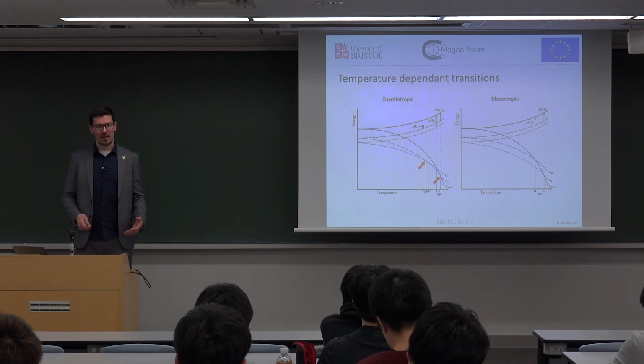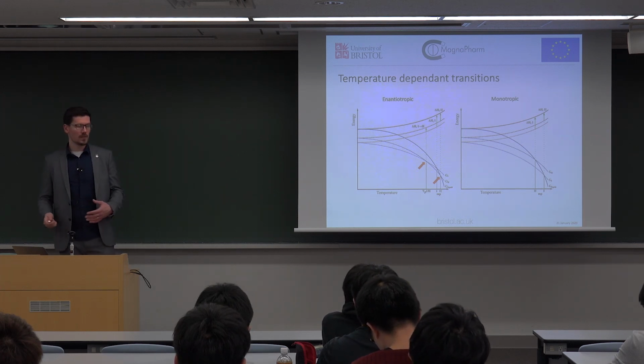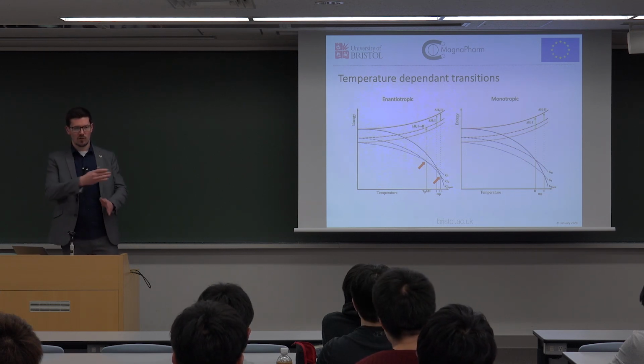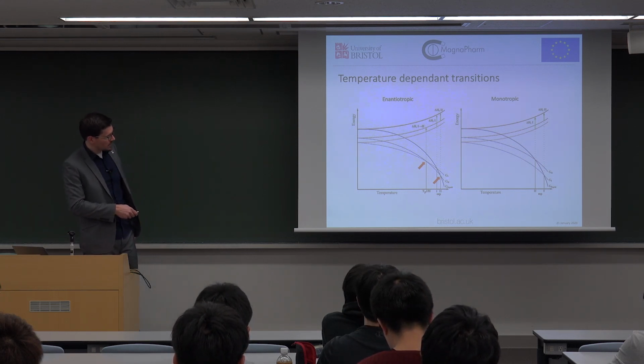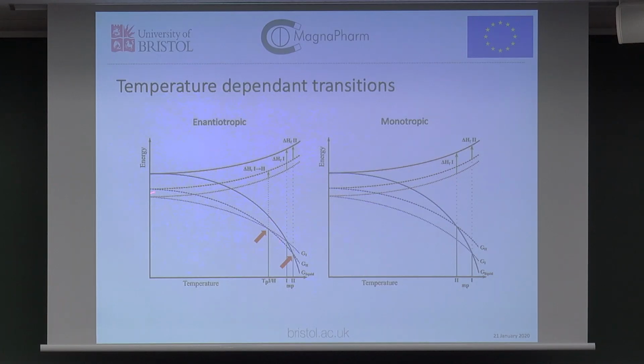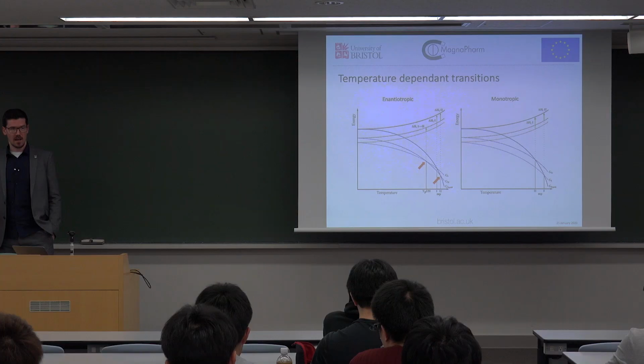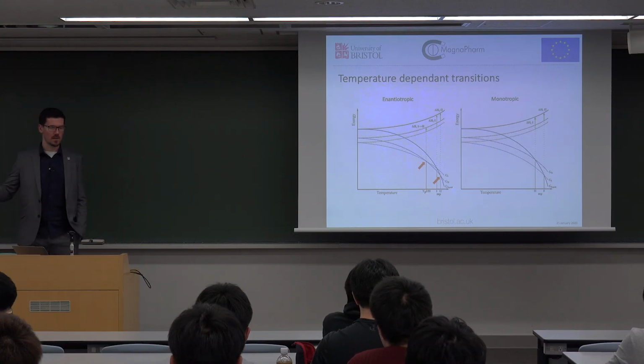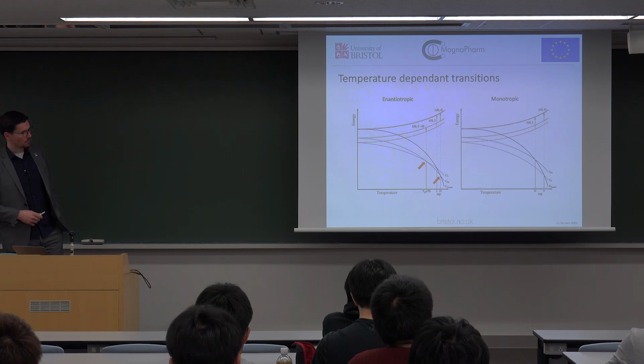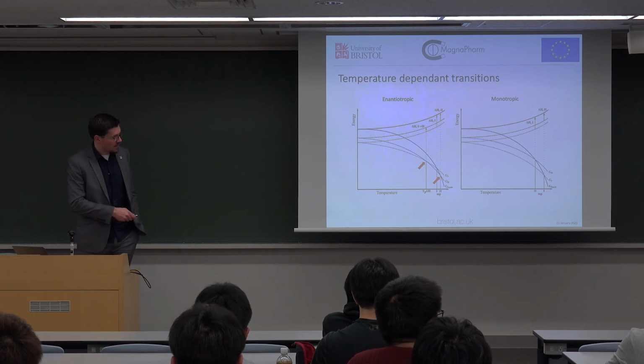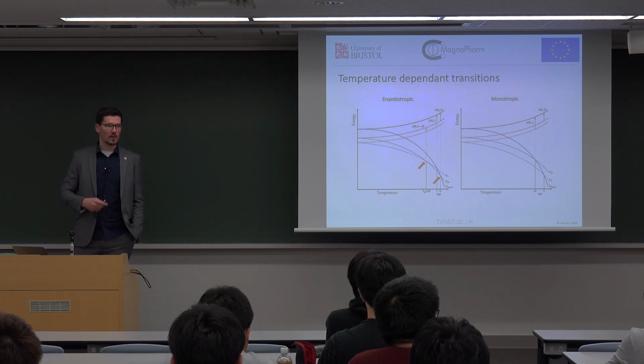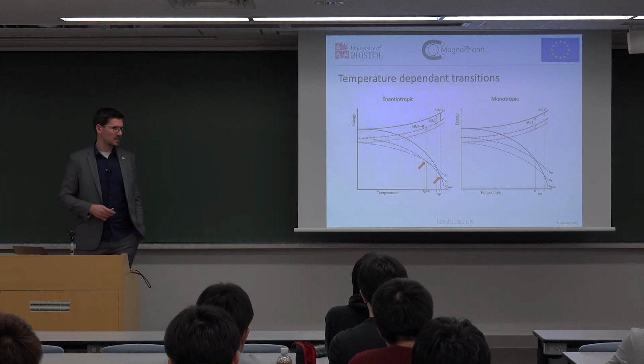Enantiotropic just means that the most thermodynamically stable polymorph changes as a function of temperature. There is a crossover of that energy. So these two dotted lines, if we think that's the energy of polymorph 1 and polymorph 2, we have transition points here and here before it melts. And they don't need to necessarily change polymorph as a function of temperature, but what they do need to do is have that energy difference. One needs to become the most thermodynamically stable. And a monotropic system is where there is no crossover. So one will always be the most thermodynamically stable, regardless of where you are with the temperature.